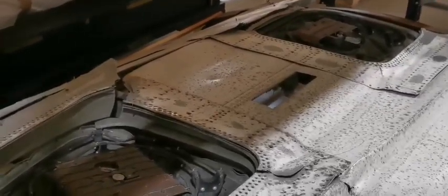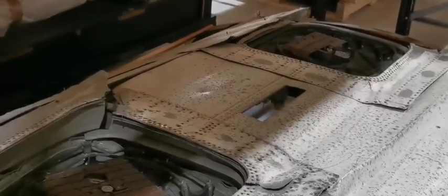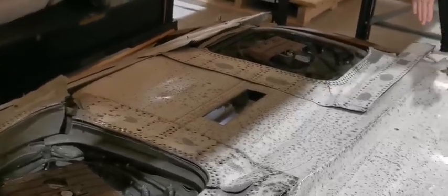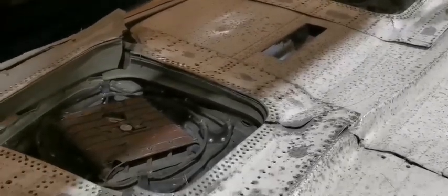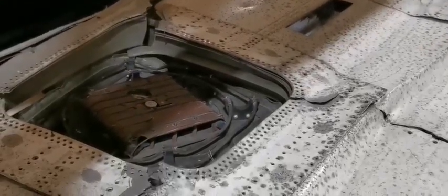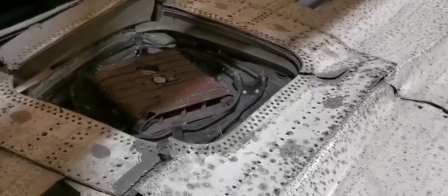Another thing was that these holes round here, in the specification, should have been drilled out, and they were actually punched out, and that caused more stress than drilling. And the whole thing was meant to be glued on, and it wasn't properly glued on. So there were a few things going on. As a result, the Comet was changed to have rounded windows and other modifications. And of course, we now know today that all aircraft have those rounded windows. We don't go on aircraft with square windows.